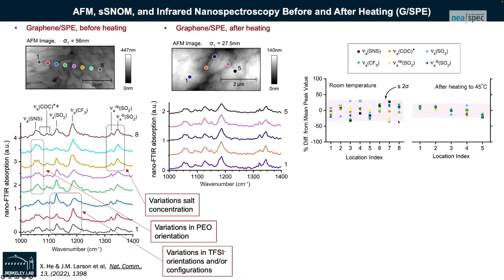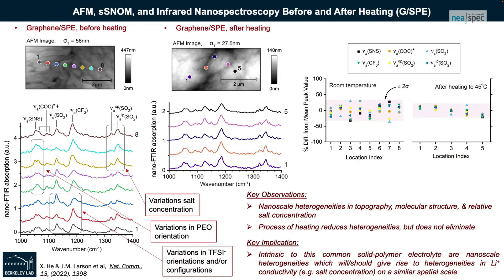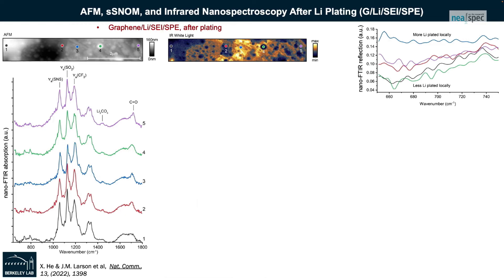This is actually relevant for subsequent electrochemical processes, because intrinsic to this common solid polymer electrolyte are nanoscale heterogeneities, which will give rise to heterogeneities in lithium ion conductivity. It's known that some of these physicochemical properties, such as salt concentration, are directly correlated with lithium ion conductivity. When we look at the interface post-plating, that's precisely what we find — a heterogeneous interface both in structure and in white light imaging, with a lot of contrast in the white light image, which we attribute to nanoscale heterogeneities in lithium plating.